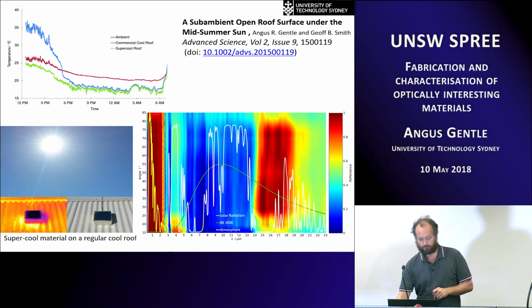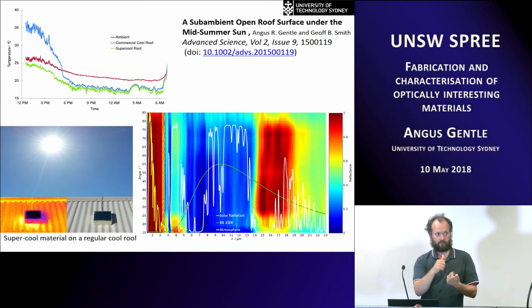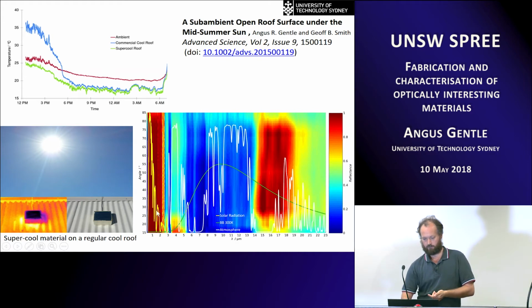So this super cool material is basically 96% solar reflecting, so it doesn't absorb very much sunlight. If you look at the spectral response, all angles reflect very well. Once there's no longer any solar, it's absorbing very strongly. This is the transmission of the atmosphere. So in the sky window, it absorbs very strongly, and then at longer wavelengths, where the sky is not transparent, it reflects again. So it actually works out quite well, and we're able to get sub-ambient temperatures on that one.